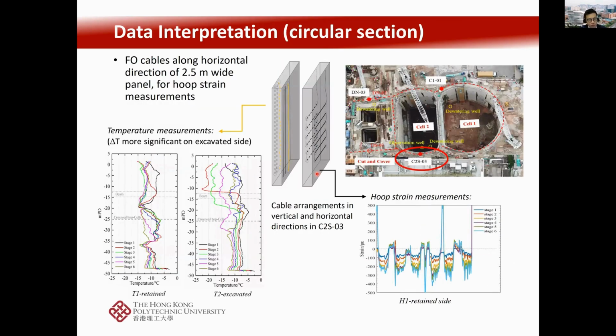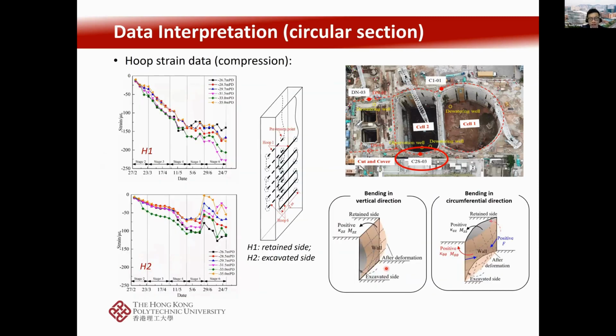But more importantly, we're trying to measure the horizontal compressive strain. So that's why we have the horizontal sections of the cables. So now we're talking about the hoop strain, which should be in compression. So in these 6 sections of the horizontal cables, we're able to see 6 profiles of the compressive strain. And again, the different colors correspond to different stages of the excavation. And then we see that we have cables arranged on the front side and also cables arranged on the back side of the retaining wall. And they actually capture different magnitudes of the compressive strain. The front side here, a bigger compression, and the back side here, a smaller compression